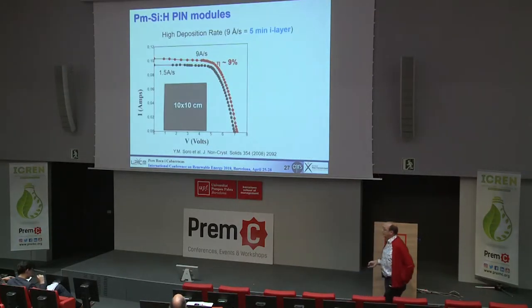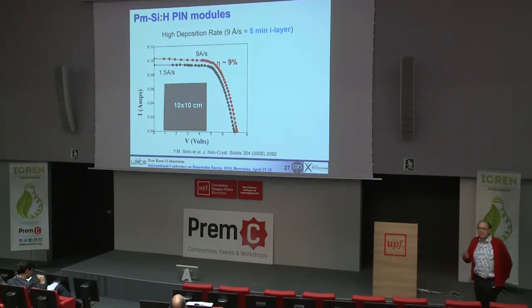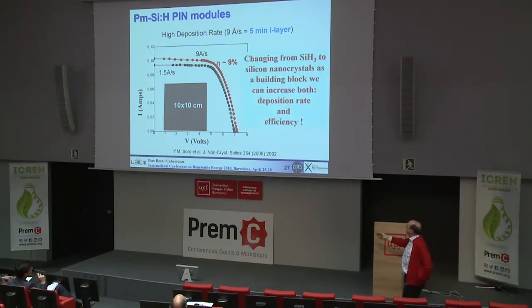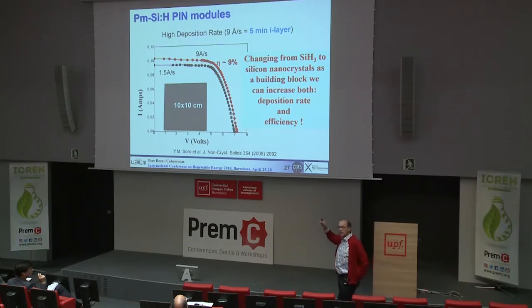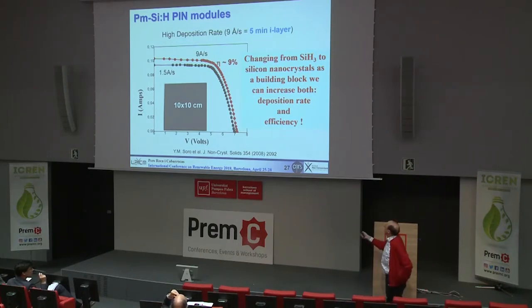And with that, we can beat Murphy. We can show that Murphy's law is wrong. Murphy says that if something can go wrong, it will go wrong. Here, what we have done is we have increased the deposition rate for this mini module by a factor of 5. And we have increased efficiency. So we can increase both efficiency and throughput. Okay. Still, the efficiency is not high enough compared to crystalline silicon.